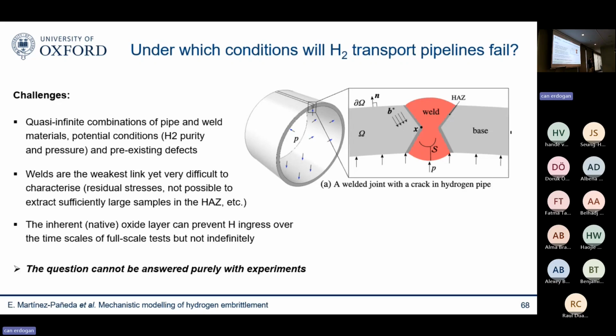The other problem is that the weakest link is welds. Welds are going to be the weakest link of your material. And it's very difficult to test welds in a lab because they contain residual stresses, as we discussed yesterday, but also the critical area is going to be the heat-affected zone, and it's not possible to extract samples on which we can do fracture tests on the heat-affected zone. And then even when you do full-scale tests, and some people are doing pipelines, it's a bit challenging because you have a native oxide layer that might not be disrupted, and that prevents hydrogen uptake, and that might not be disrupted during the duration of the full-scale test, but will be disrupted over the decades that you're operating.